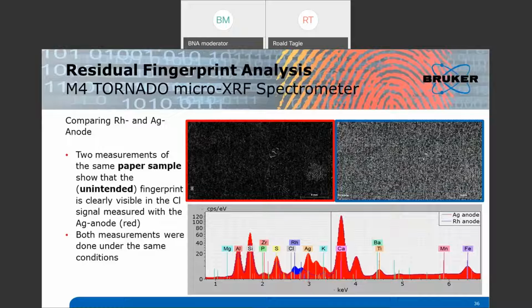So basically, the silver tube is more sensitive for detecting chlorine. In this case, it's a paper with a non-intended fingerprint on it. Basically, the same measurement conditions, one with a silver anode and the other one with a rhodium anode. And what you see here, very similar to what we were showing and discussing before, is that on the left side, where you have the silver anode elemental distribution for chlorine, there is a very clear signature of at least one fingerprint, and some traces of another one, whereas on the right side, which is the rhodium image